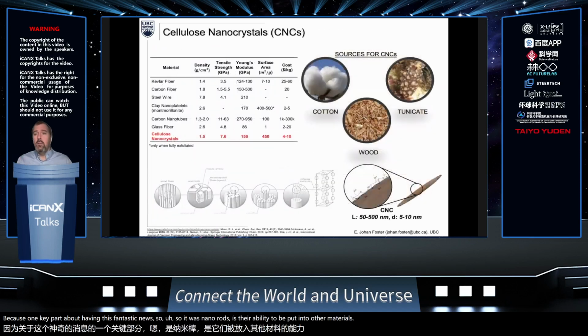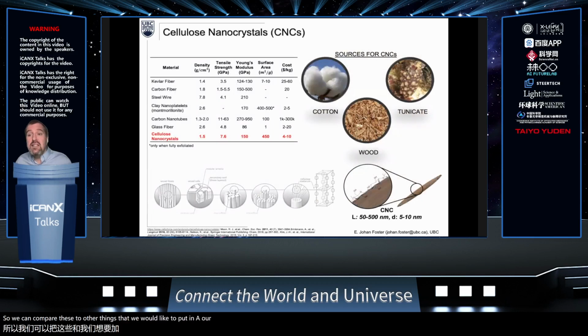Okay. So we can compare these to other things that we would like to put into, say, a polymer. When you talk about a tire on your car, for example, reinforcing that rubber with, say, Kevlar or carbon, fantastic materials. In the case of, say, steel wire, really strong, fantastic material, but is very, very heavy. So on a car, that's not so important. But if you were trying to reinforce materials in, say, an aircraft or something that flies, you want to be very cognizant of how much that weighs. So at the bottom, we've got cellulose nanocrystals, which have a density of about 1.4, 1.5, have a fantastic Young's modulus, anywhere between, say, 100 and several hundred gigapascals, a high surface area, and potentially a low cost. So these can be a nice material.